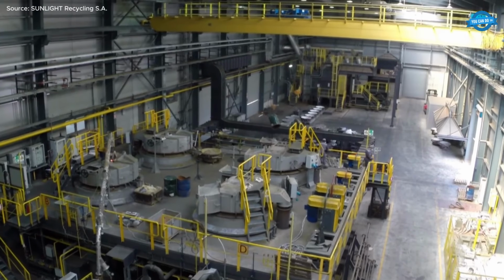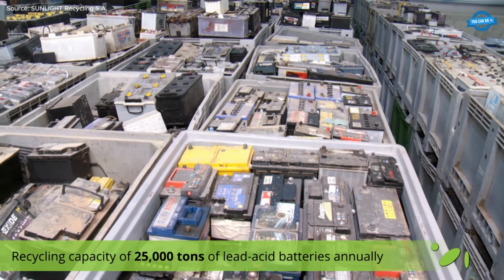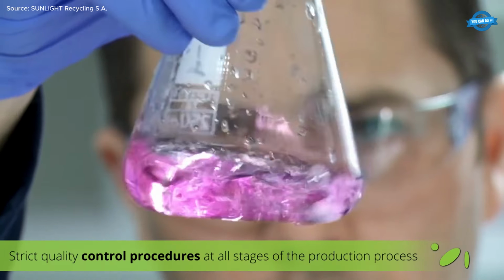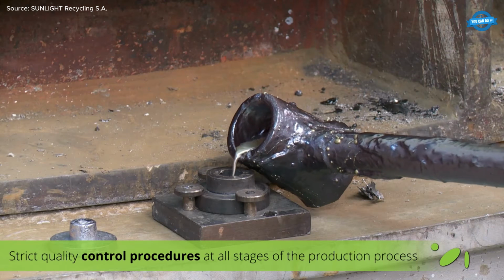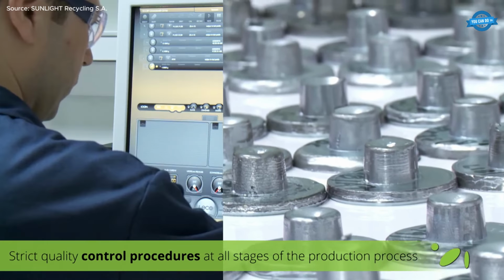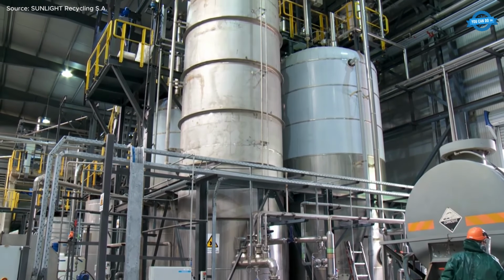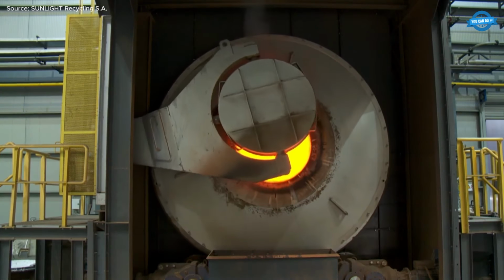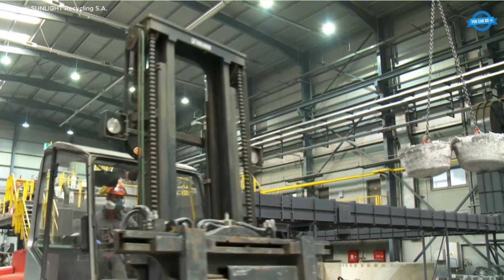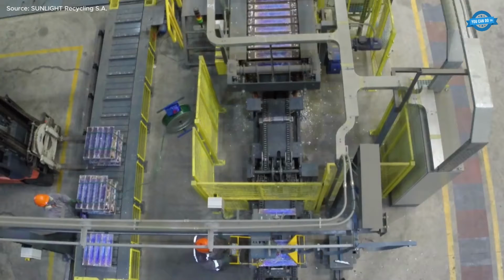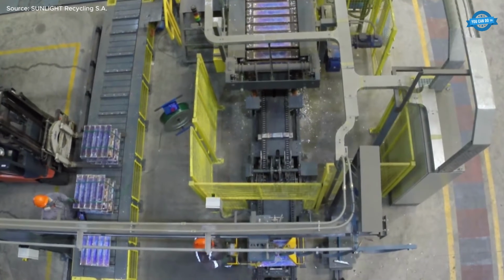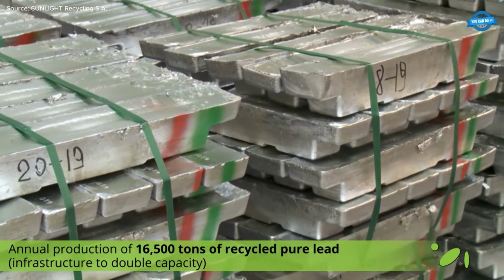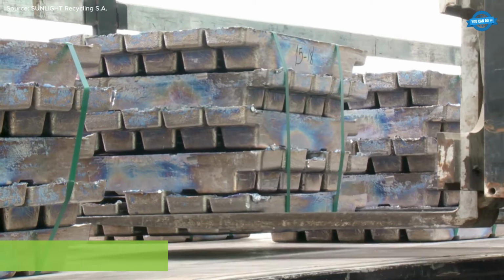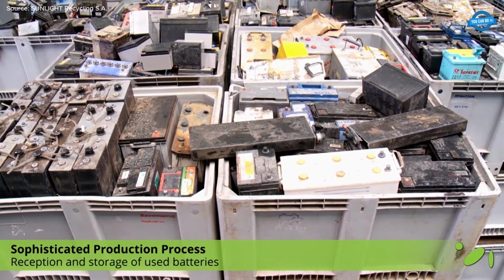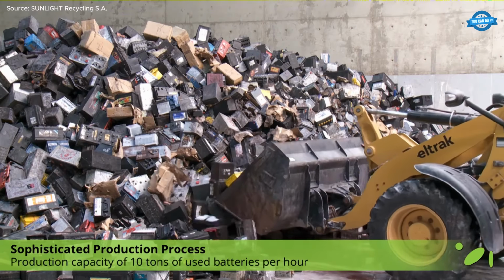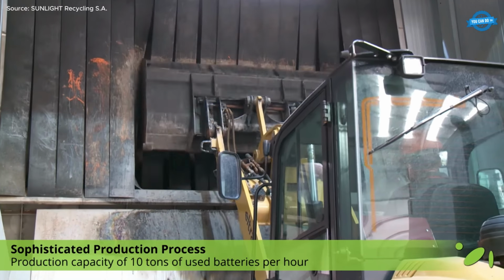Sunlight Recycling applies a holistic, fully integrated approach to lead-acid battery recycling, combining high-efficiency material recovery with advanced environmental controls. The process begins with the reception and secure storage of used batteries, supporting a throughput of up to 10 tons per hour. Batteries are mechanically crushed, and materials are separated into polypropylene, lead-bearing fractions, and electrolyte. Polypropylene is recovered at high purity, while the electrolyte undergoes 2 desulfurization stages, producing industrial-grade anhydrous sodium sulfate through controlled neutralization.